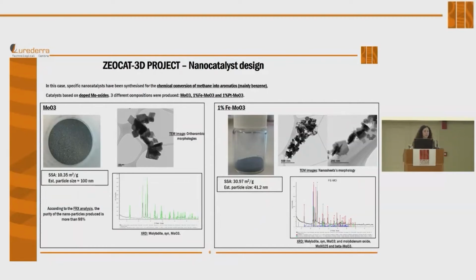In this project, we have produced different nanoxides based on molybdenum for the chemical conversion of methane into aromatics. Firstly, we started with the production of simple molybdenum, in which we got an estimated particle size of around 100 nanometers. And then we started doping this simple molybdenum, and among the different dopants, we worked firstly with iron.